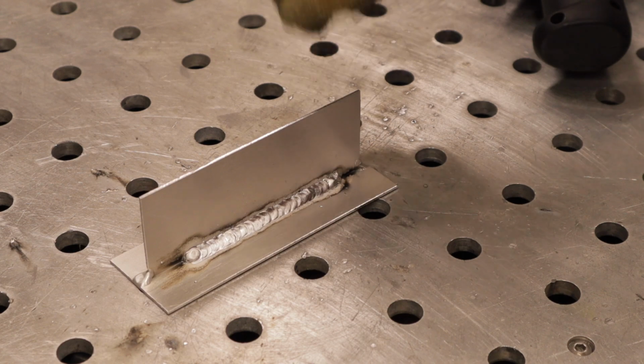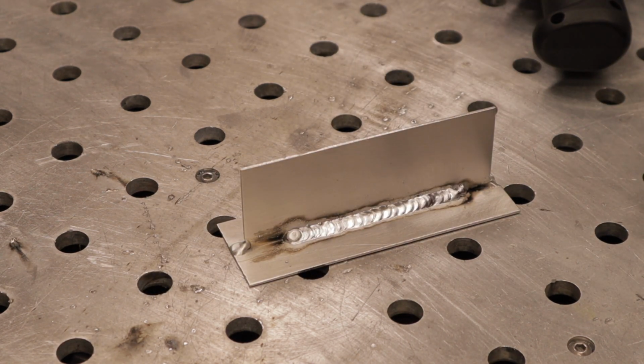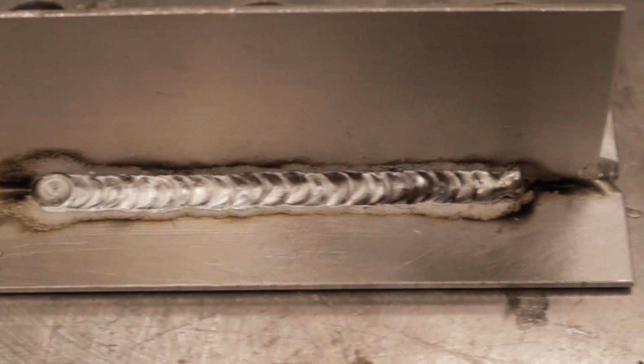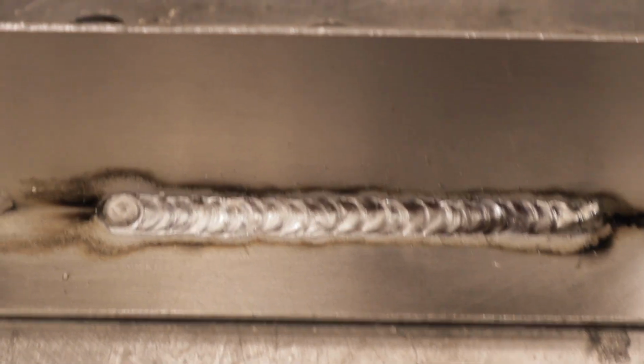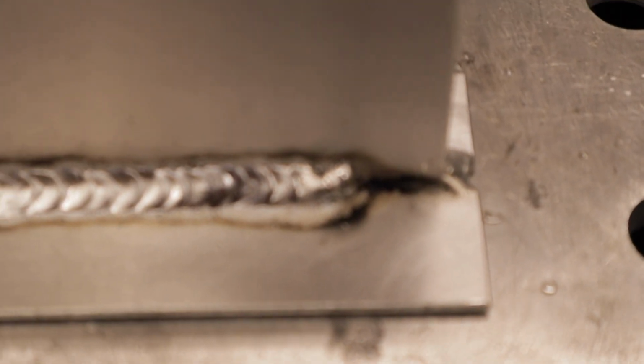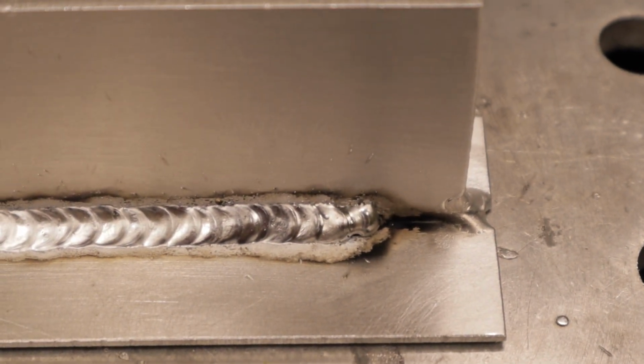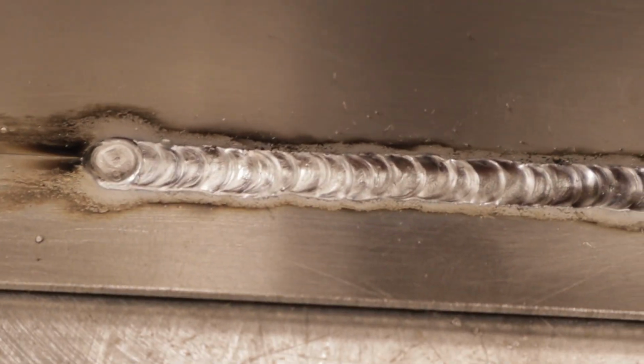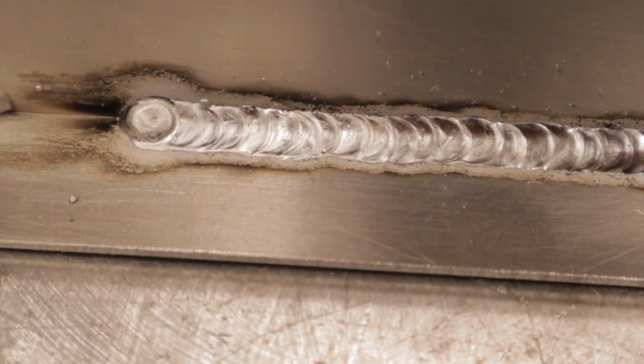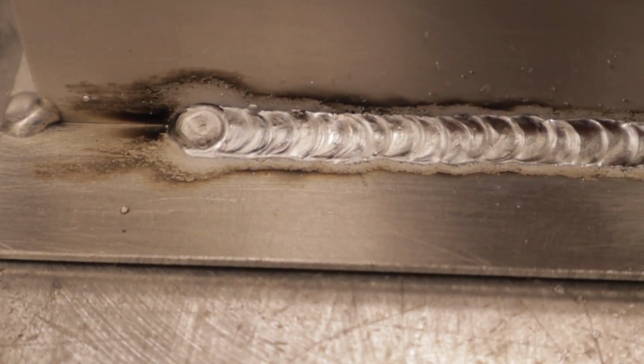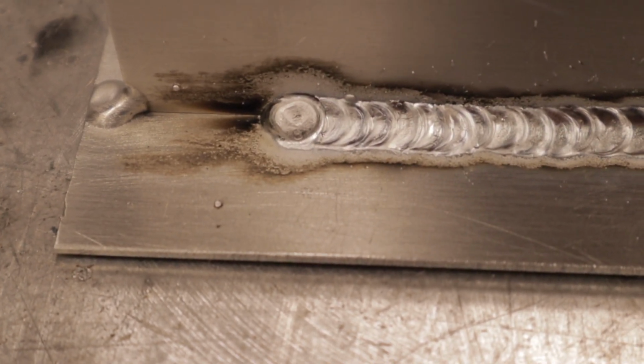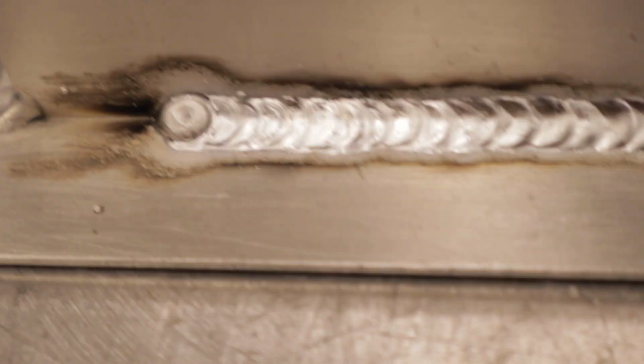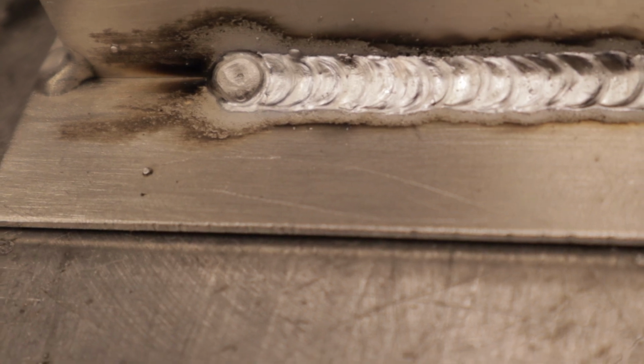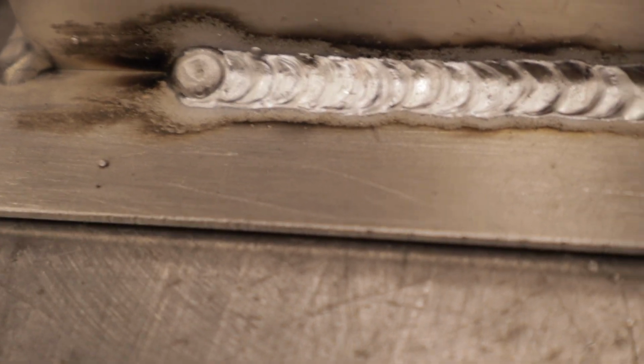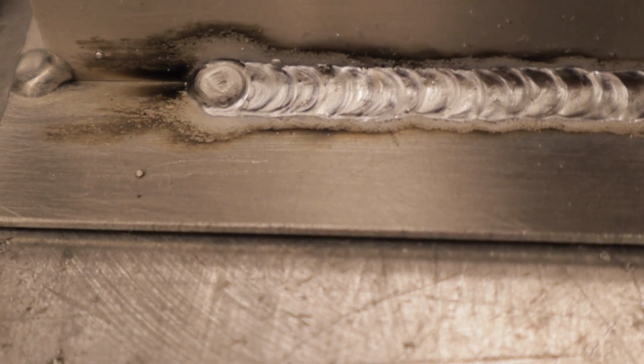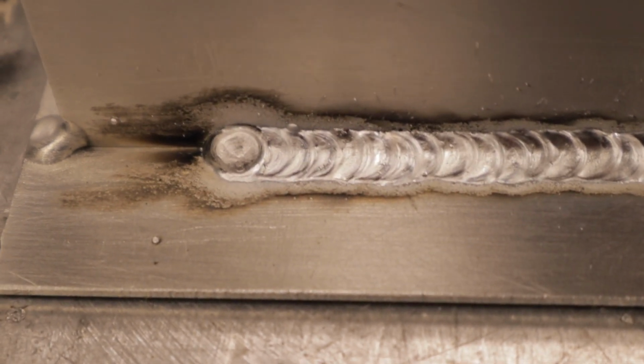All right, that's 16th inch aluminum. That's pretty sweet. You can see I'm still a little bit cold on the beginning. I'm gonna have to increase the amperage on that, but you'll see that the face of the weld is nice and clean. And you can see how I use the 4T at the end to fill in the crater with a button. This helps to prevent cracking in the end of the weld, and so that is why you'll hear different tones in the arc as I go along.